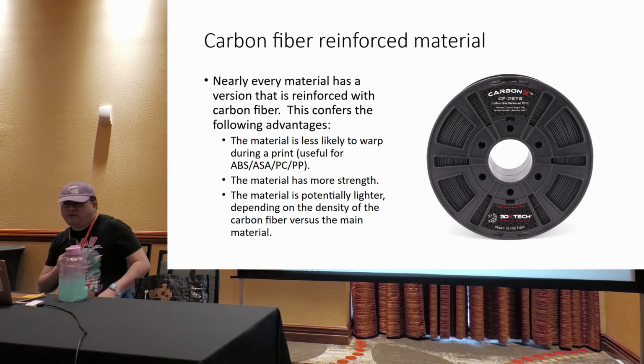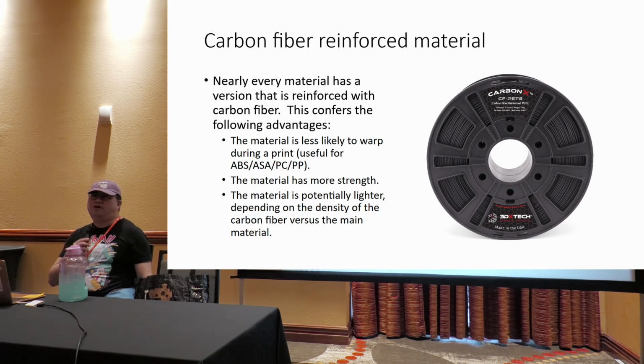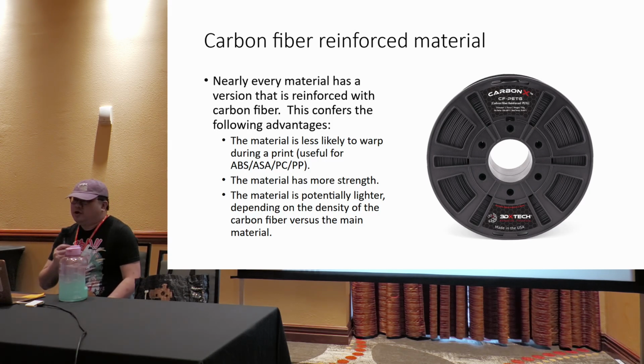So every material that you have heard of, PLA, ABS, PETG, nylon, polycarbonate, there's always some company that has infused it with carbon fiber. And this does a lot to the material. First thing, it actually makes the material easier to print because the carbon fiber causes less warping. So if you're having issues with warping and your enclosure is not helping, you may want to try one of these materials because they definitely warp a lot less.